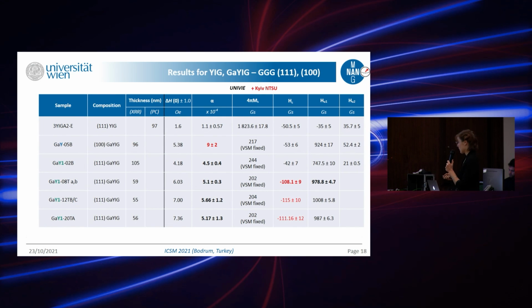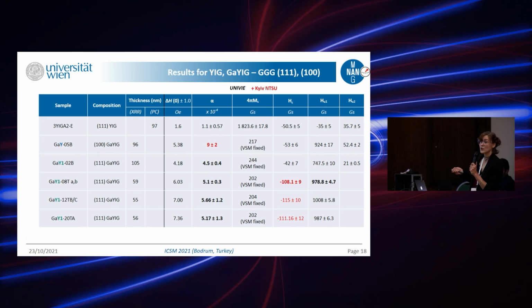And these are the results. As you see, it's ongoing work, so some gaps will be filled. First of all, the reference YIG has a typical value of 1,800 Oersted. But with around 1% of gallium, we already see a 9-time reduction of saturation magnetization. It's already 200. While the uniaxial one, which was 30, is now around 900 or even 1,000 Gauss. At the same time, pay attention that Gilbert damping has increased, but it's still a very good value, still on the order of 10 to the minus 4.